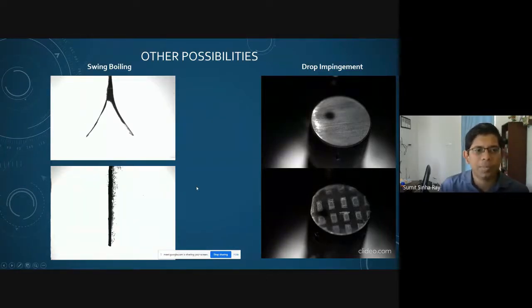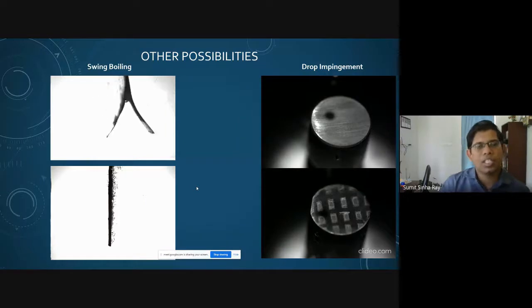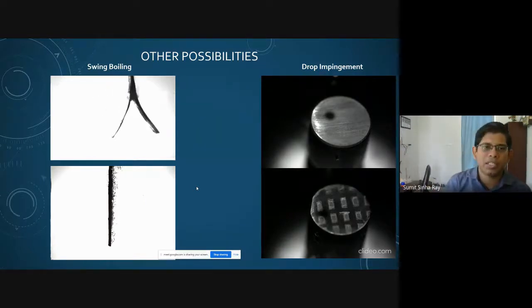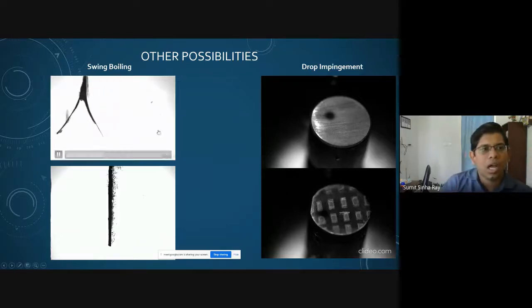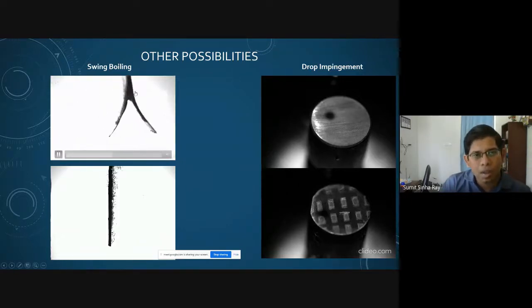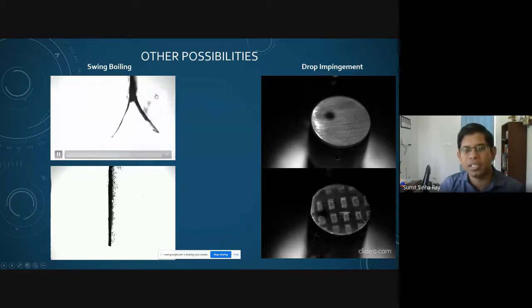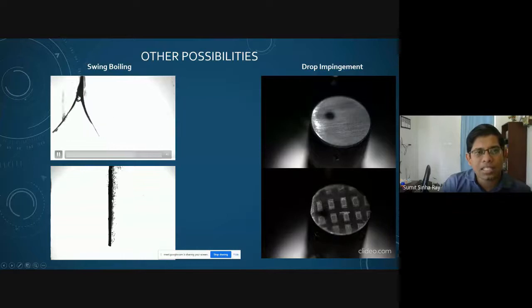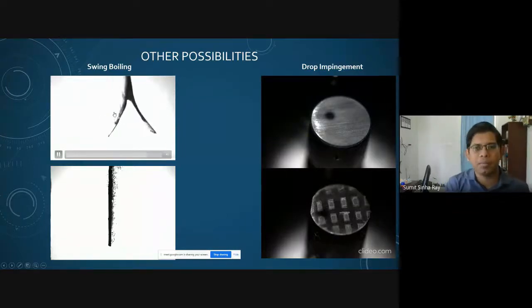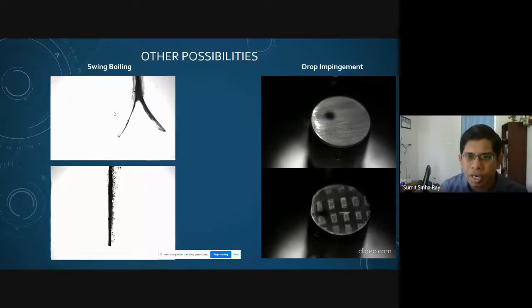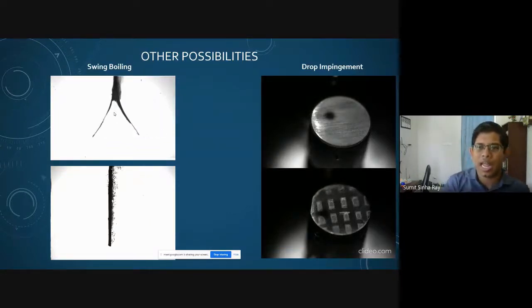This is one experiment, what we call swing boiling. Since a bubble has to leave vertically for buoyancy to take place, we had this condition where the bubble leaves from the surface normal to it, and hence buoyancy does not play any role. This is a self-actuating motion governed by the nanotextured surface on a particular heater, which is being turned on and off as it gets hot and cold, and then it swings, and it moves into the liquid, and it kind of dissolves all the bubbles that have formed, and then delays the vapor layer formation that generally happens in zero gravity.